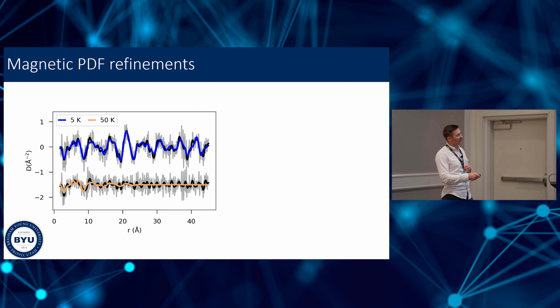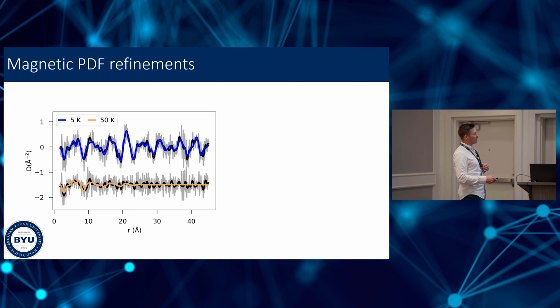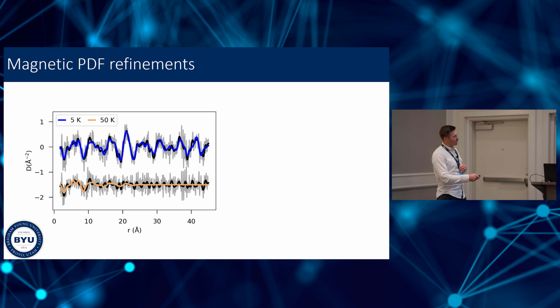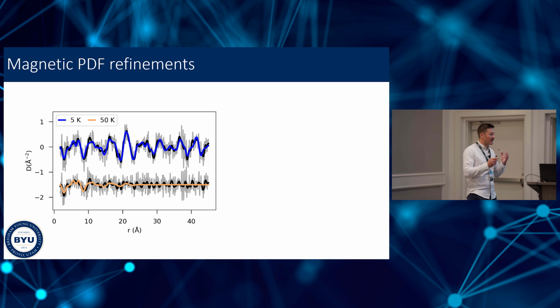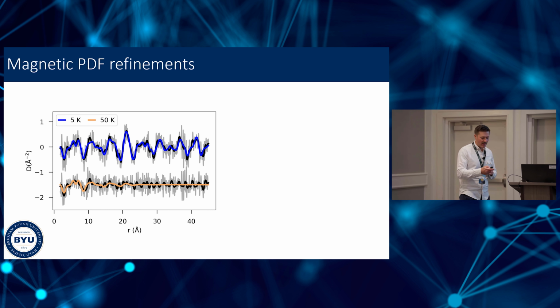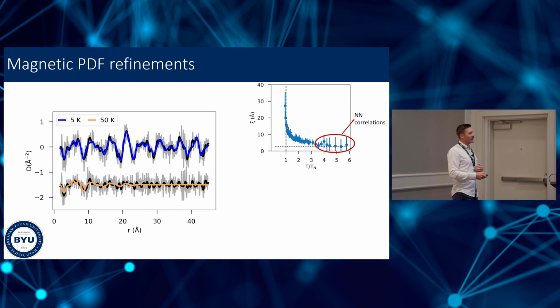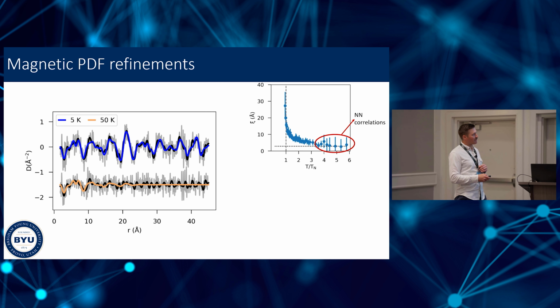So here I've isolated just the magnetic component of the neutron PDF data. At 5 Kelvin, we have a nice long-range antiferromagnetic ordered state. And we know that it's long-range because these wiggles are persisting out to large distances, whereas at 50 Kelvin, above the ordering temperature of about 44 Kelvin, we have only short-range correlations. But nevertheless, these short-range correlations persist. They are there in the paramagnetic state. So we can look at the temperature dependence of the correlation length, of the local magnetic order parameter, all of these things that we've done before.